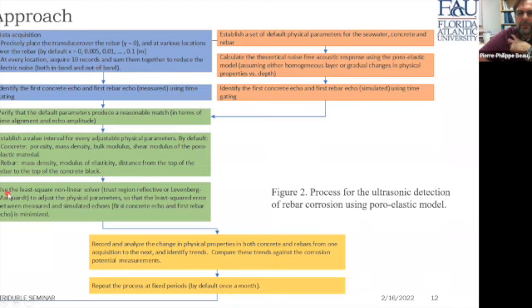And afterwards, we use a nonlinear solver. Right now, we use the trust region reflective algorithm or the Levenberg-Marquardt algorithm to adjust the physical parameters so that the least square error between the measured and simulated echoes, that is the first concrete echo and the first rebar echo, is minimized. Afterwards, we record and analyze the change in physical properties in both concrete and rebars from one acquisition to the next to identify trends. We compare these trends against the corrosion potential measurement and repeat the process at a fixed period. By default, that will be once a month.